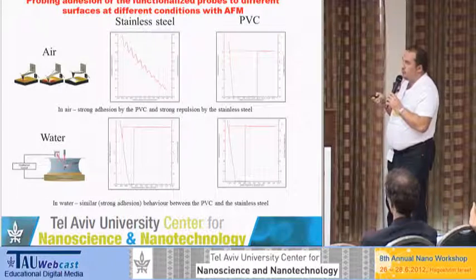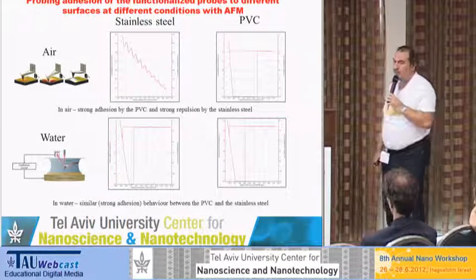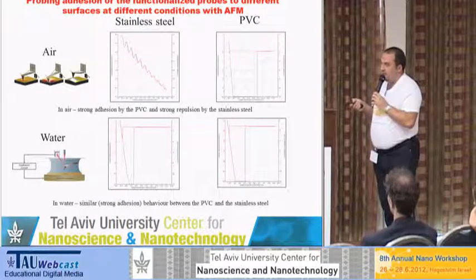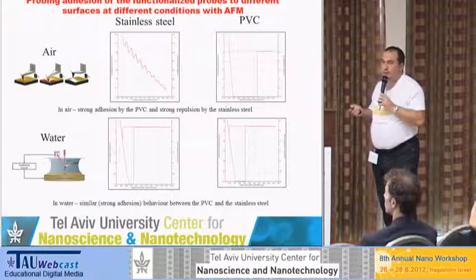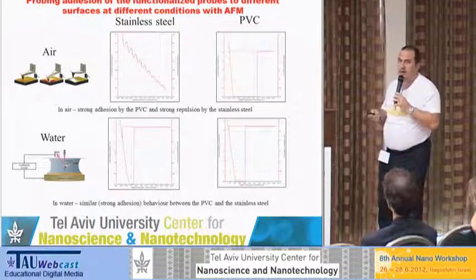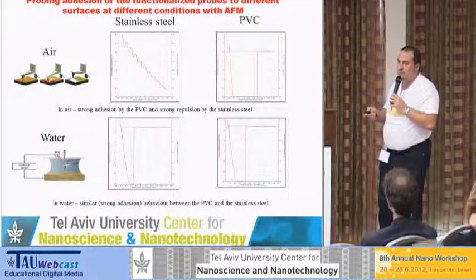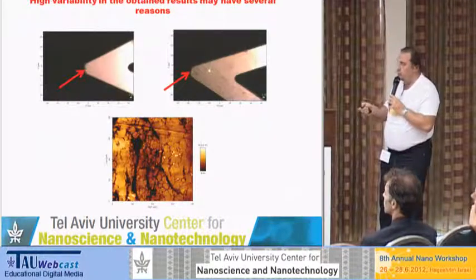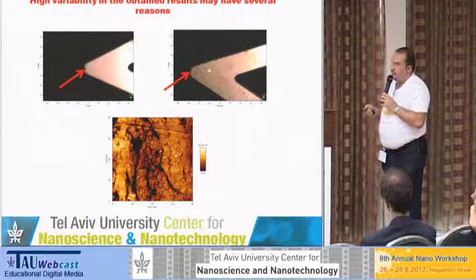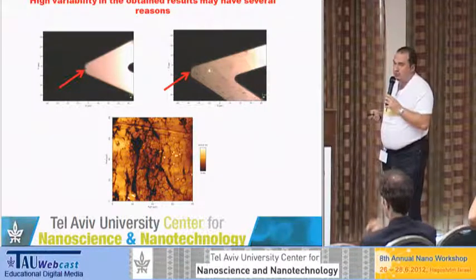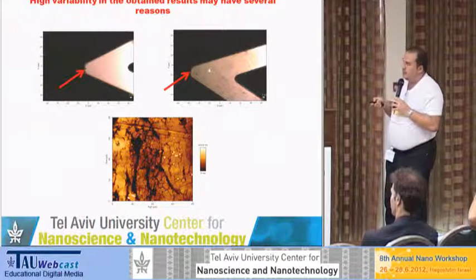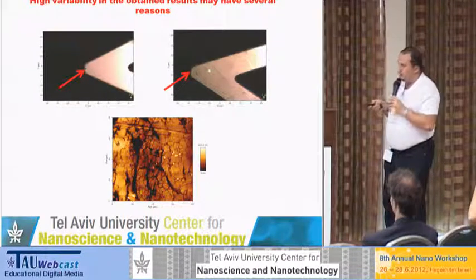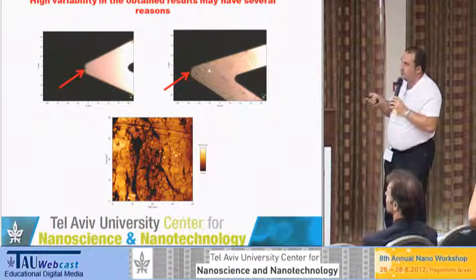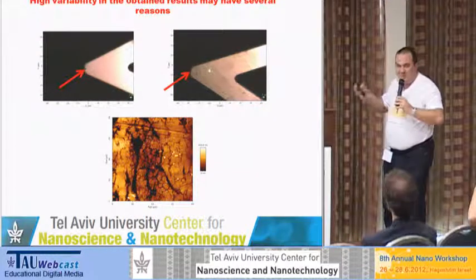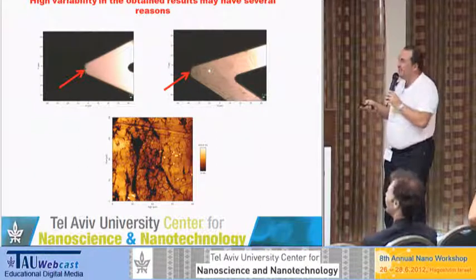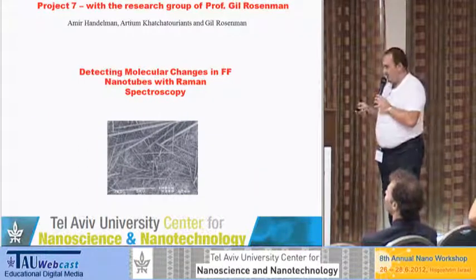In water, both these surfaces exhibited adhesion. So this is quite remarkable. Unfortunately, as I mentioned, there was very high variability in the further results, so I do not present them right now. I just want to mention that there are several reasons for such variability, such as surface roughness of stainless steel and that the bead was detached. I need to hurry up, so I will try to make it a little bit faster.